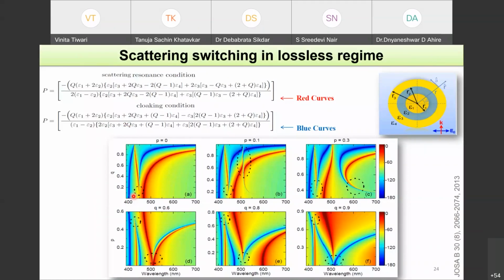So one interesting feature is where this high and low scattering states are getting merged. And this is wavelength. So it means that at that particular wavelength, this high and low scattering states are very close to each other. So you can switch between them by slightly changing the incident light wavelength. And what is shown here is that at different dimensions of this three-layer structure, you can obtain many such conditions where high and low scattering states are getting merged.